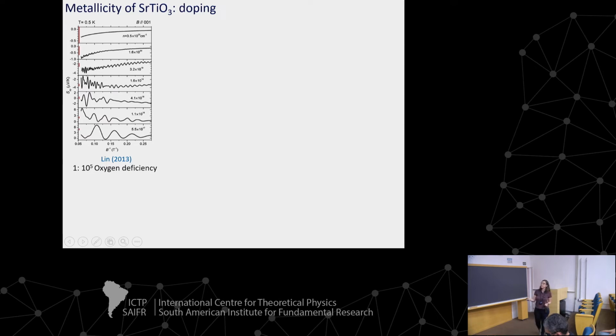But here, interestingly, we are now talking about more recent work, in the last decade, and this material, for a very low level of concentration, can show a quite well-defined Fermi surface. This is an experiment of the Nernst effect. So how can we understand the metallicity of this system? Why we cannot see the same metallicity, for instance, in silicon, is due to the Bohr radius.